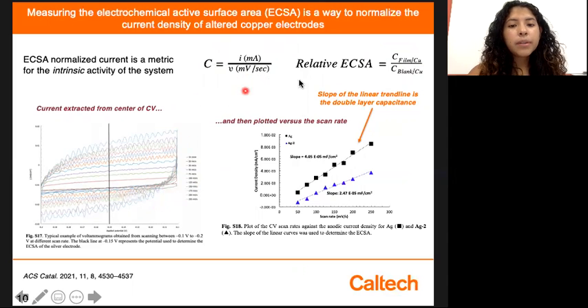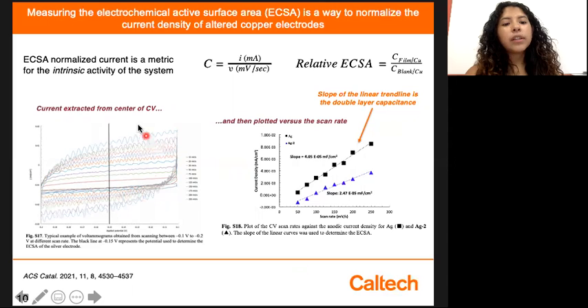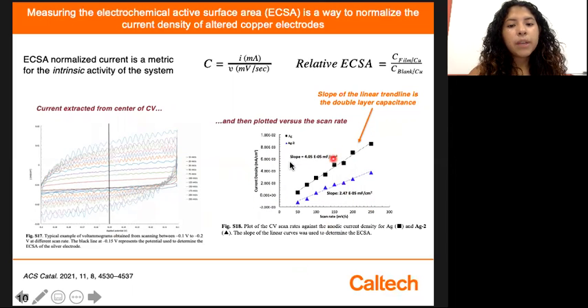And the way they were able to solve for the capacitance is using cyclic voltammetry. They plotted the current versus the applied voltage. And if you can see, these different colors are the different scan rates. They extracted the current from the center of this voltage window and then plotted it versus the scan rate to find the slope and use that slope as the value for the double layer capacitance.